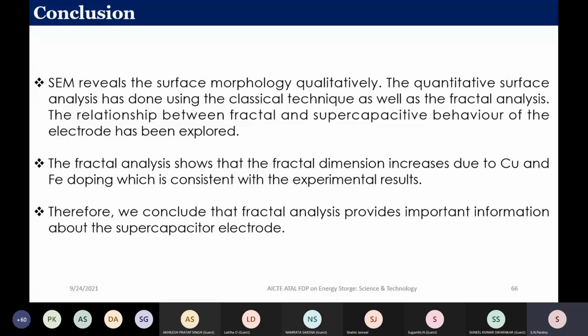The fractal analysis shows that the fractal dimension increases due to the copper and iron doping, which is consistent with the experimental result. So therefore, we conclude that fractal analysis provides important information about the supercapacitor electrode. And here I would like to mention that this is the very first time that our group has used this fractal concept in the supercapacitor.